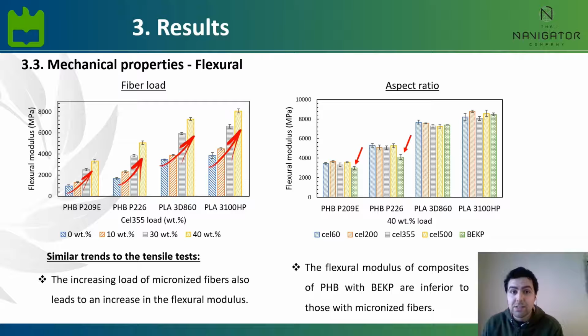Both these results in the tensile and flexural properties probably have to do with the effect of the lower compatibility between the PHB and cellulose fibers, as I said before, together with the high aspect ratio of this non-treated bleach eucalyptus kraft pulp, which leads to weaker resistance of the composites upon stretching or bending.